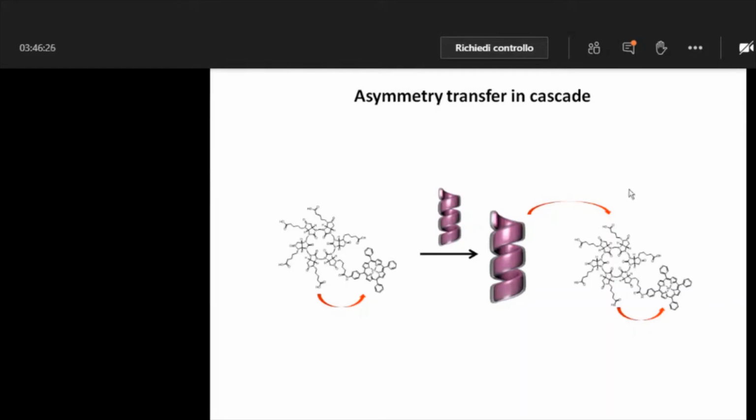What is interesting is, even though the main interaction happening inside the helices is between the cucurbituril and the Gemini ions, and the porphyrin is more in a remote fashion, the final CD induction happens at the porphyrin. So the entire system is quite useful for sensing of chiral molecules, and the chromophoric properties of the porphyrin can be used as evidence to show that these huge cucurbituril molecules can actually be put inside the supramolecular helices for a large number of sensing studies.